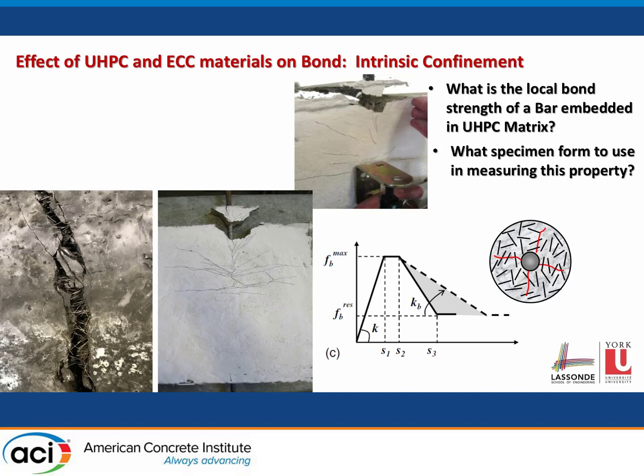And of course, in order to embark on an experimental study that would assess bond behavior of bars embedded in UHPC, one needs to address a couple of issues, which are, first of all, how short an embedment length would one have to use in order to claim that they have obtained a local bond? And what kind of specimen type one would have to consider. The second question is, of course, a more critical one than the first, because the kind of specimen form and setup seems to affect significantly the kind of bond properties you can obtain.